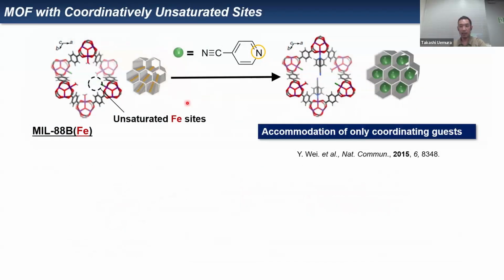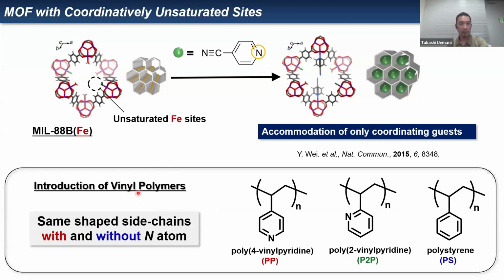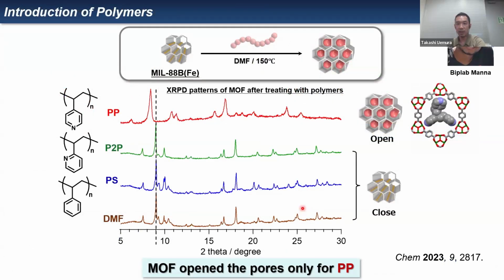Here we employ this MOF with a coordinatively unsaturated site that can allow the accommodation of only coordinating guests. So we try to introduce these vinyl polymers with same-shaped side chains with and without nitrogen atoms. Here, and nothing here. Next we checked the XRD after the treatment with these polymers and found that the MOFs opened pores only for this polymer that can interact with the pore wall effectively.